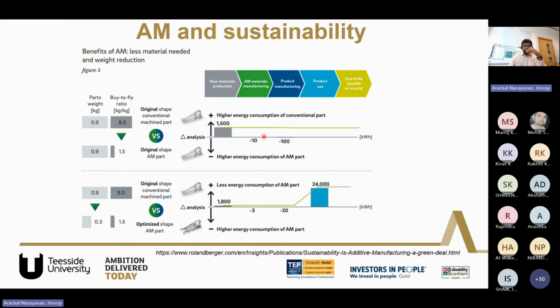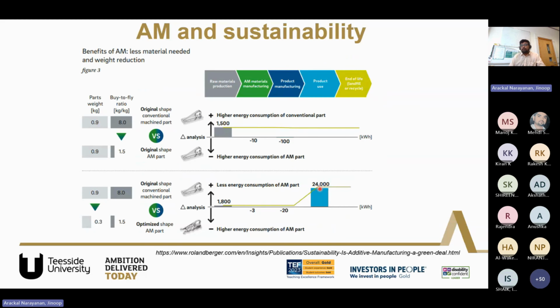Again, if you optimize, in this particular case, we didn't optimize the design for additive manufacturing. If you're using additive manufacturing and optimizing the design for additive manufacturing, you can reduce the weight of it considerably, that is 0.9 kg to 0.3 kg, then you have more benefits in terms of the product usage. So if you see, there's 24,000, the unit is kilowatt hour per kg. So we have 24 megawatt hour per kg as a savings when you use additive manufacturing, the lightweight additive manufacturing or the optimized additive manufacturing product in the product use stage. So this brings a lot of benefits. So if the same product is used, then we can have a very high level of cost savings, and then we can use additive manufacturing for that.